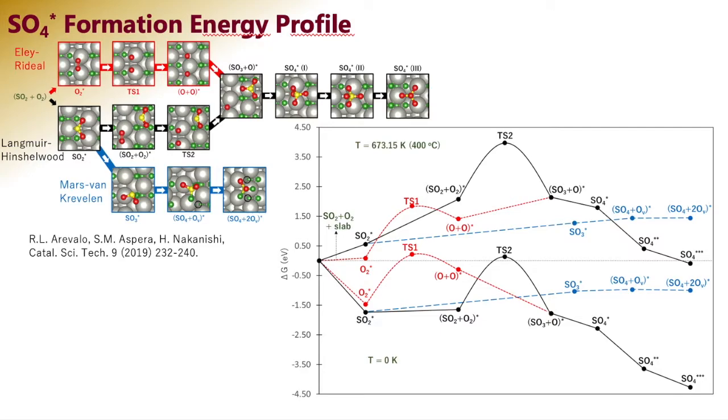the reference state. These results show that despite the highly exothermic SO2 oxidation on the palladium oxide 101 surface via the Eley-Rideal and Langmuir-Hinshelwood mechanisms, its kinetics can be limited by the high barrier for O2 dissociation. On the other hand, the Mars-van Krevelen mechanism has low exothermicity for the overall SO2 oxidation process, but is expected to promote more favorable kinetics because of the relatively facile elementary steps.